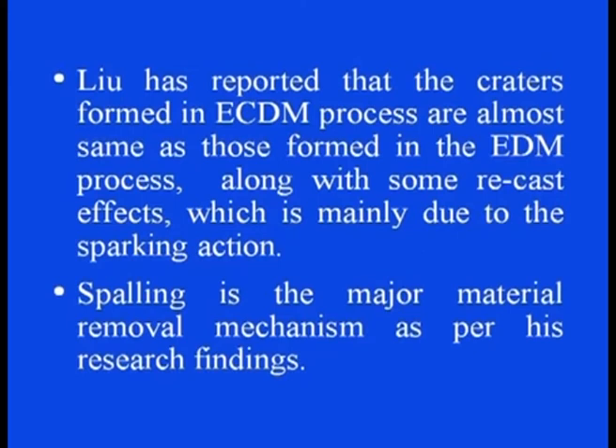Jain and his group have used alumina glass composite ceramic material and found that the machining rate is greatly affected by porosity of the samples. The results also show that the material removal occurs by attack at the grain boundaries, most probably due to the etching process. Liu has reported that the craters formed in the ECDM process are almost the same as those formed in the EDM process, along with some recast effects, which is mainly due to the sparking action. Spalling is the major material removal mechanism as per his research findings.